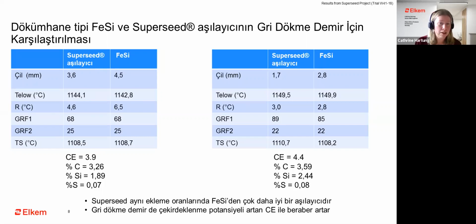And a more favorable difference between the graphite factor 2 and graphite factor 1. You would like to see a low graphite factor 2 and a high graphite factor 1. And the solidification ends at a higher temperature in both cases, suggesting that your solidification ends with a greater safety versus the metastable temperature. And you should have more good looking or the right type of graphite in the case of the high carbon equivalent iron compared to the lower equivalent iron. But in both cases, you will see that Superseed is a better inoculant than foundry grade at the same addition. So what you could do then is reduce the Superseed addition to make them perform equal.